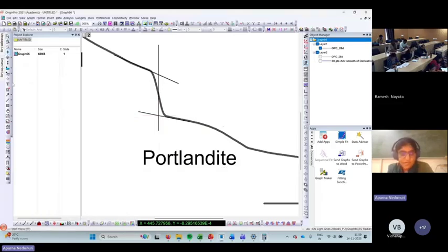The same method we will adopt to determine the amount of CaCO3. In CaCO3 also, you'll have a tangent that we place here, and another tangent that we place here. We'll take a vertical line and place it in such a way that this area and this area are almost equal. Or you can always have your DTG curve and keep the vertical line at the peak of the DTG curve at that particular point, and then take the y-intercepts. From these two y-intercepts, you can now calculate the amount of calcium carbonate.